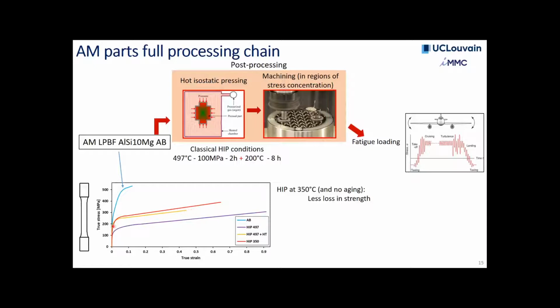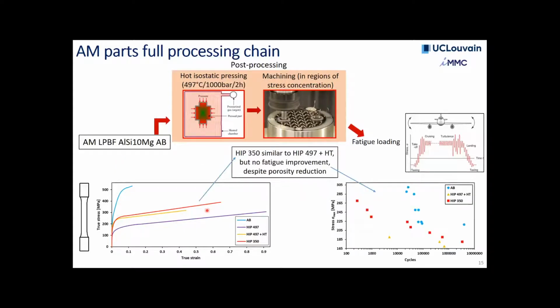application. Now, as you can see here, this 350 degrees heat treatment was really good in terms of ductility, giving similar conditions of strength. So we were very happy with that. But then when you're looking at the fatigue life of all these samples, you see we kind of gave up on the 497 degrees heat treatment because it was really not good compared to the as-built material. The 350 degrees, well, was lower, and this is probably due to the lower strength.